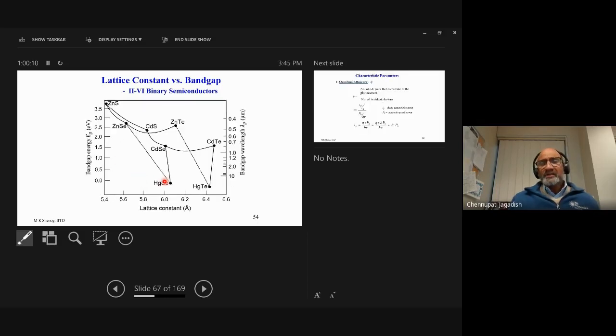What about other semiconductors? We talked about II-VI semiconductors, particularly in terms of photodetectors for defense applications, where we want to go to longer wavelengths where the atmospheric windows are, the 8 to 14 and 3 to 5 micron regions, and that's where mercury cadmium telluride plays an important role. Also, mercury telluride and cadmium telluride have very close lattice matching, so by mixing these you can make a wide variety of detectors.